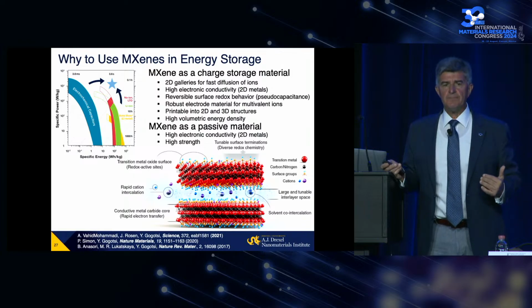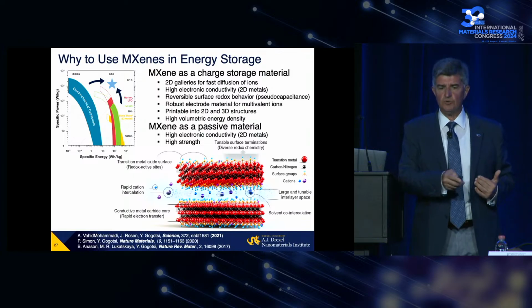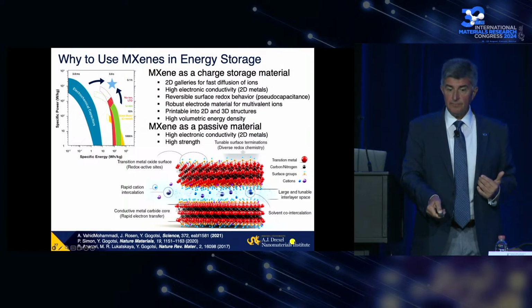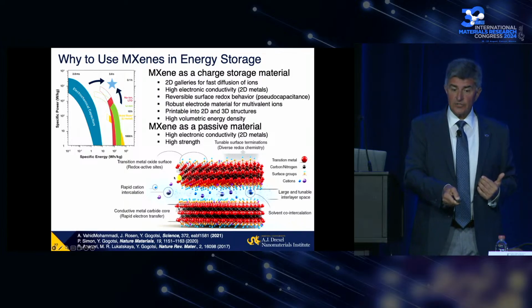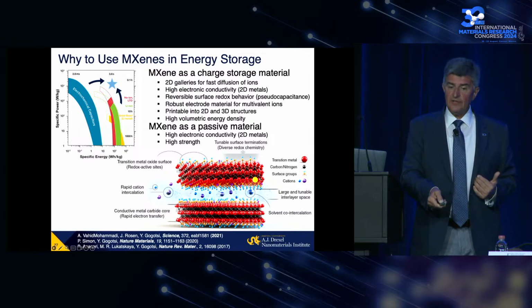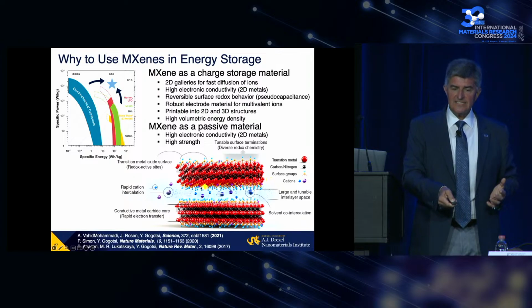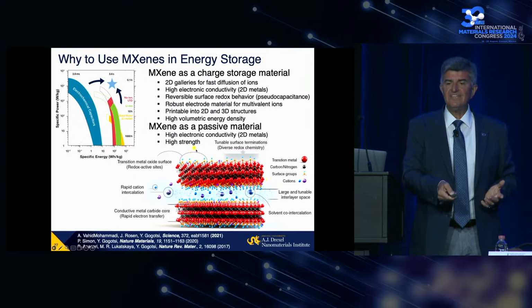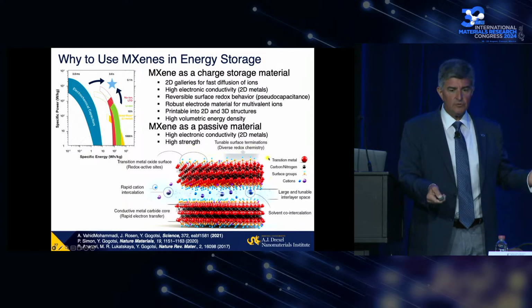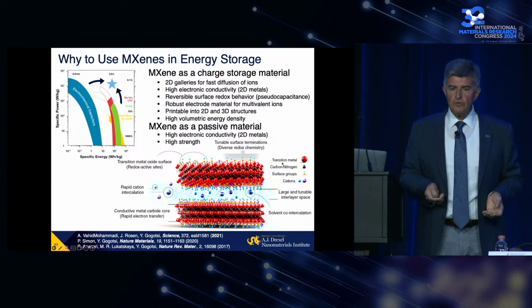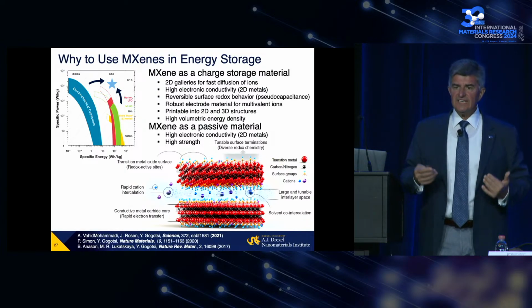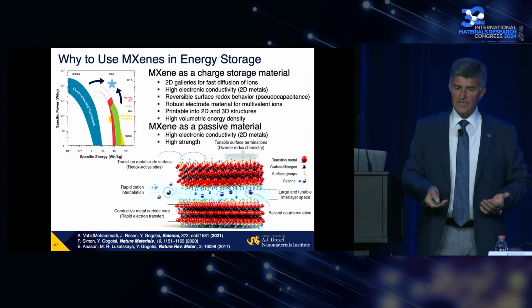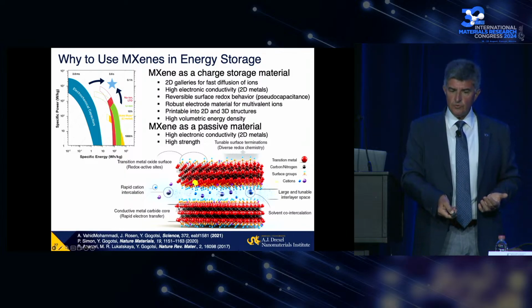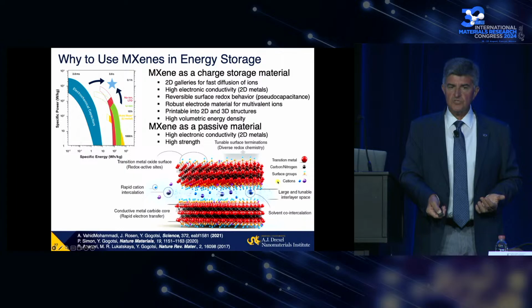So fundamentally, we're limited in charging batteries to a large extent by insufficient conductivity. And additive of a couple of % of carbon nanotubes cannot solve this problem here. MXenes conduct electrons, they conduct ions between the layers, and they have redox active metals, vanadium, molybdenum, niobium, titanium, the same that are used in many current battery materials. So we can have redox energy storage. We're not limited by solid state diffusion because everything happens on the surface.